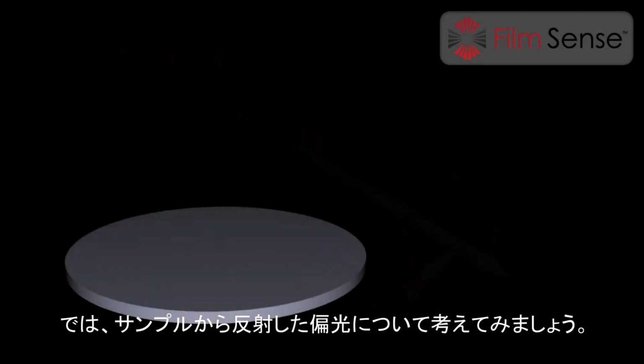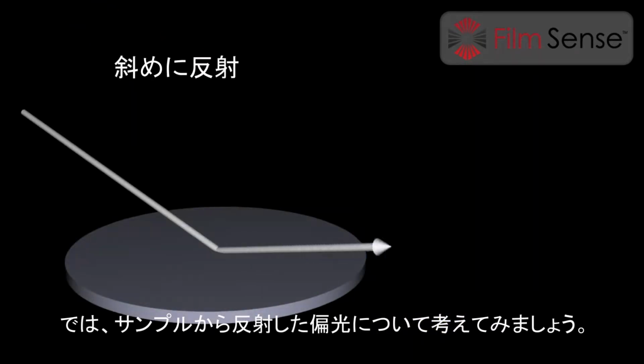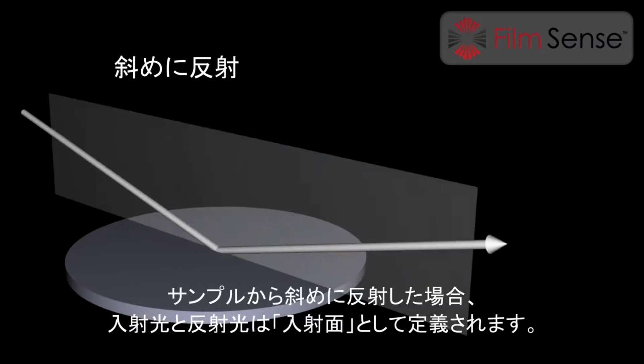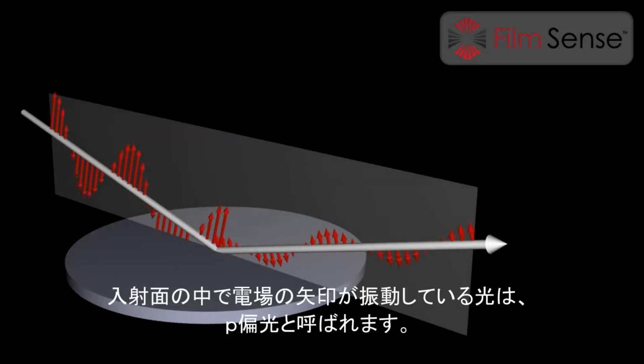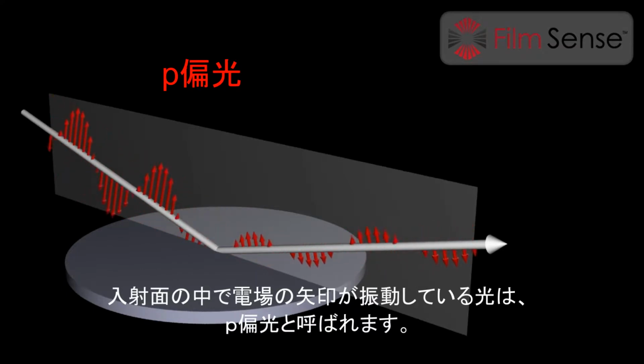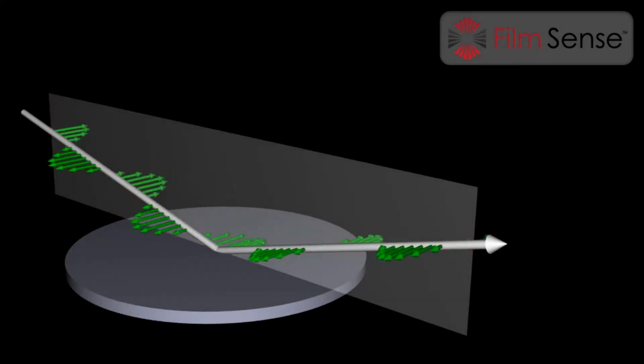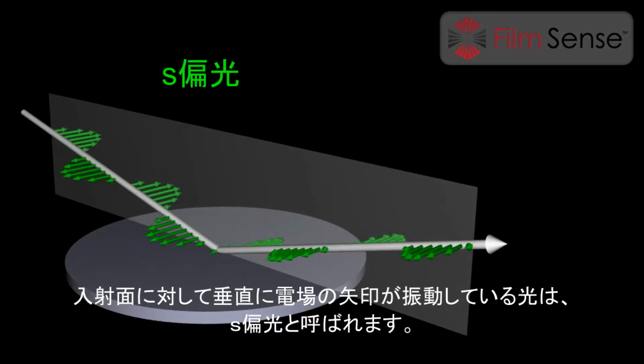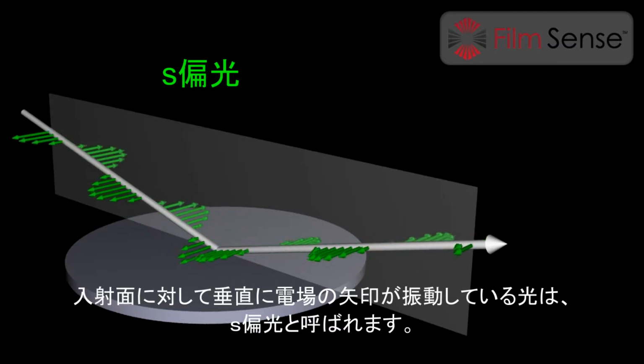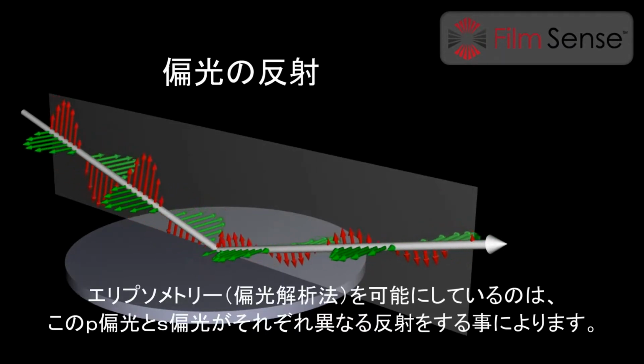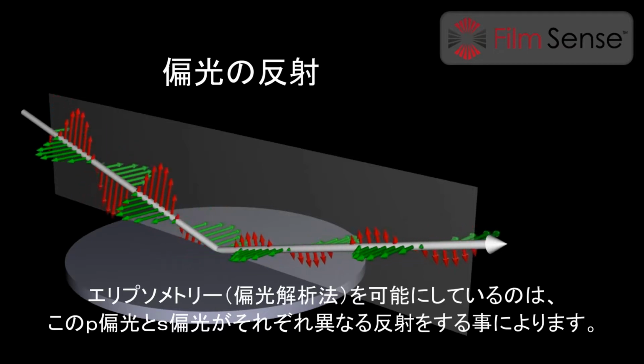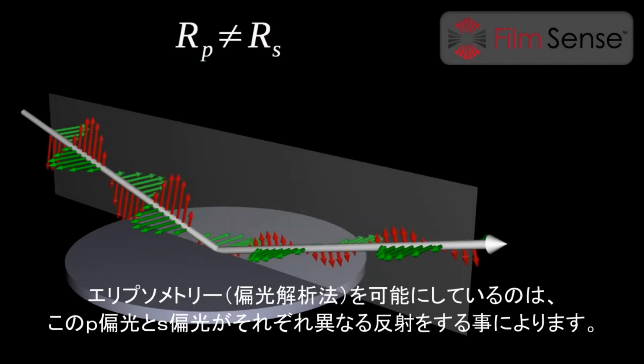Now let's consider the reflection of polarized light from a sample. When light is obliquely reflected from a sample, the incident and reflected beams define a plane of incidence. Light with its electric field vector oscillating in the plane of incidence is called p-polarized light. Light with its electric field vector oscillating perpendicular to the plane of incidence is called s-polarized light. The enabling principle of ellipsometry is that p and s-polarized light reflect differently.